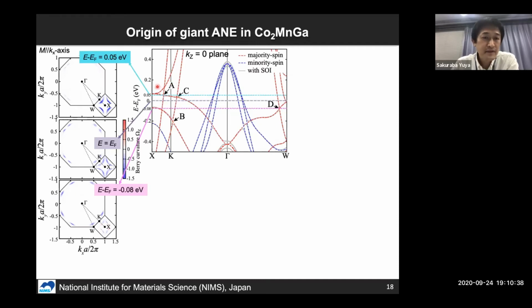And if you see the calculation of Berry curvature at this energy level, 0.05 eV, as you can see, large Berry curvature appeared in between the K point and X point. So this point corresponds to the gap point indicated by A. And if you see the Berry curvature at minus 0.08 eV, strong Berry curvature appears in between gamma and W point. So this point corresponds to this D. So this opening gap is the origin of large Berry curvature near the Fermi level in this material.